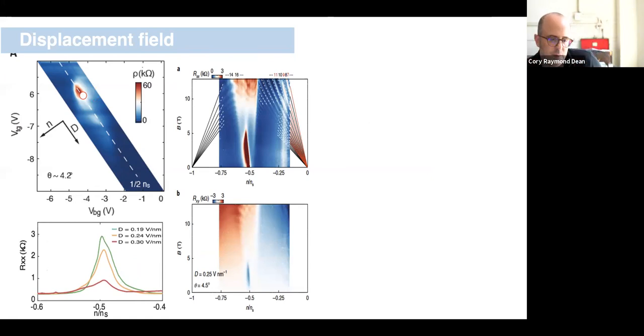So one of the ways we do that is we look at the magneto transport around this half band filling point. That's what I'm plotting here on the right. So the top is plotting longitudinal magneto resistance, and the bottom is plotting the Hall resistance.